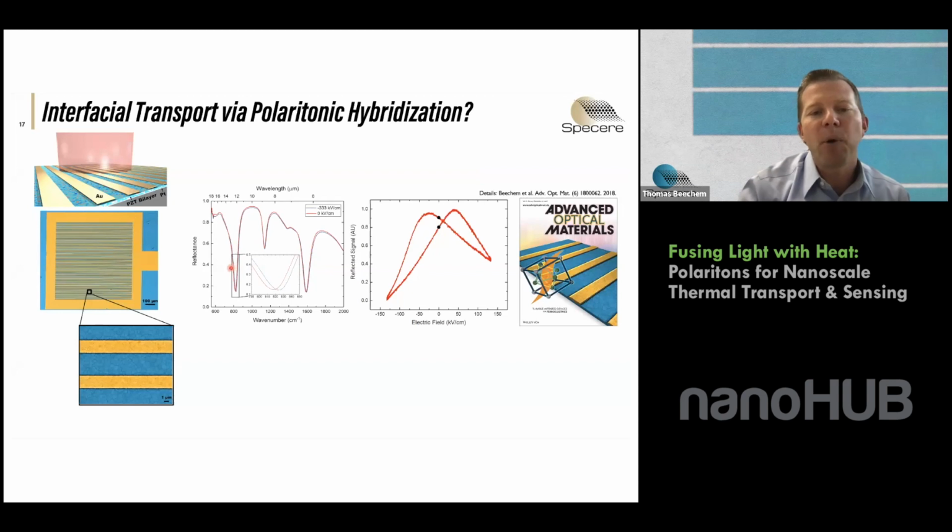And then we would pole the ferroelectric and we could show that we could tune it to some level. If we looked at it as a function of the electric field that we put across it, we could see this nice butterfly loop that is characteristic of a ferroelectric. And what's nice about a ferroelectric, of course, is there are different polarization states. And so we could use its remnant polarization to have it live in two different states that would latch.